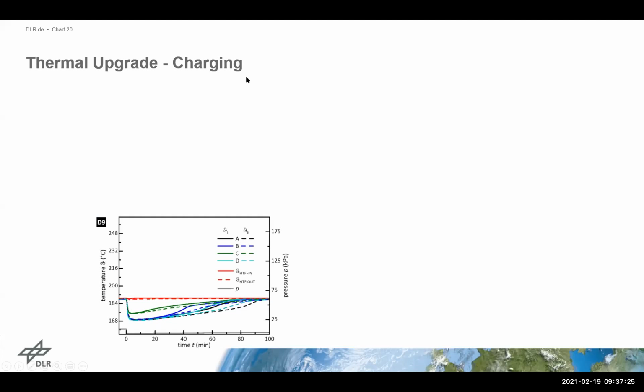Very quickly, some results. We have a charging temperature here in red at, let's say, 185 degrees Celsius. This is the heat transfer fluid temperature. And what you see in this diagram is this controllable reaction. So as soon as the valve is opened, the material immediately dissociates, releasing water. This has to be condensed in the connected condenser, and you see the endothermal process is initiated and starting, and we have something like 15 Kelvin of temperature difference in order to drive the heat transfer to the chemical reaction.